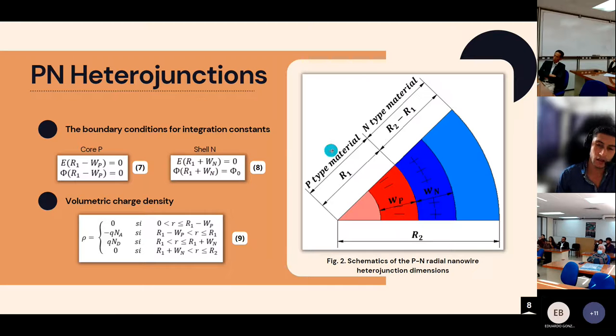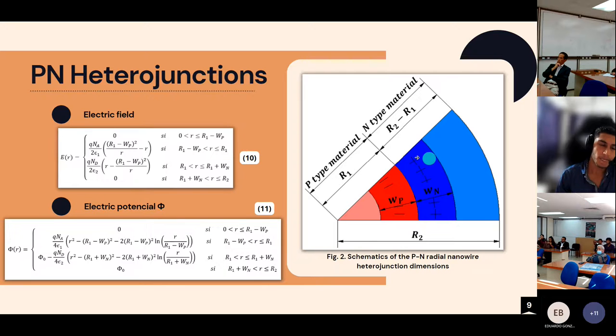And when we consider the volumetric charge density, that is the fundamental charge times the acceptor density in the P side of the semiconductor, and the fundamental charge times the donor density in the N semiconductor, we get the electric field and the electric potential functions for the whole device. The electric field and the potential are piecewise functions for the four zones in the device.